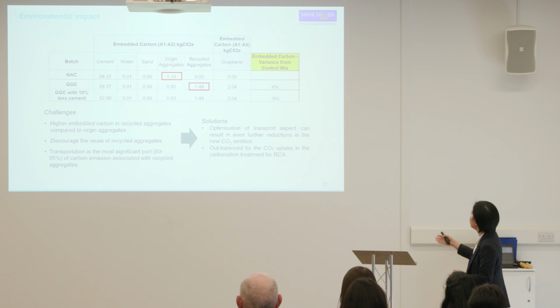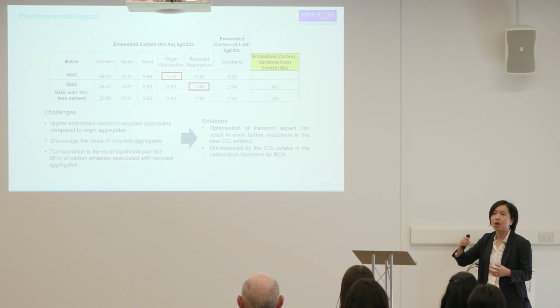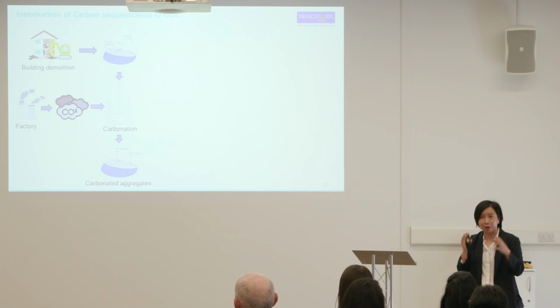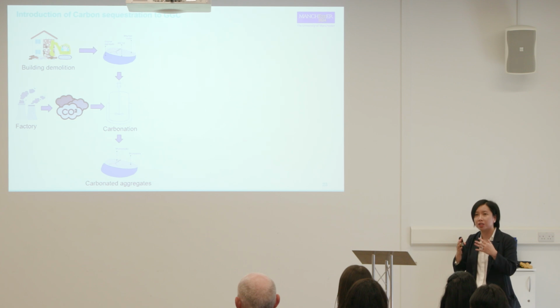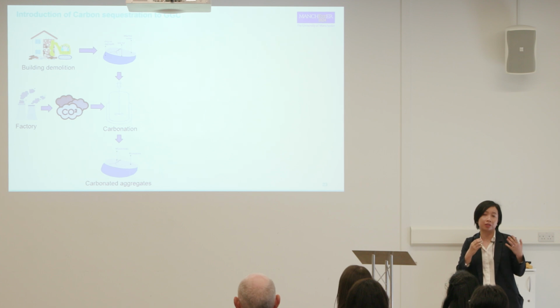So my research group has been exploring various solutions, and we found that there are two promising solutions. One is to optimize the transportation distance, basically, and improve the co-location strategy. And second is to offset the embodied carbon by the carbon dioxide uptake in the carbonation treatment for recycled aggregates. So, as an ongoing project, we are now exploring introducing carbonation to the recycled aggregates. And theoretically, the carbon dioxide from cement manufacturing or concrete manufacturing or any other factories could be the source for carbonation.